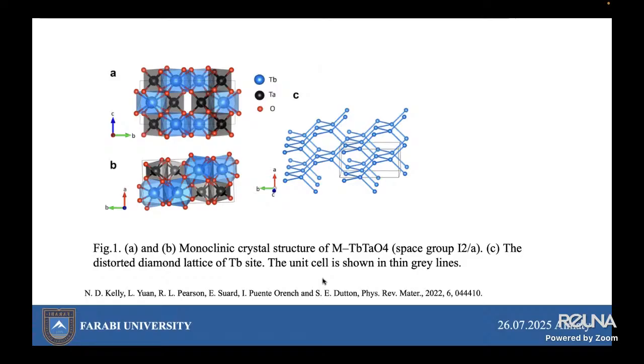Here, below a temperature of 1.2 Kelvin, a slight increase in the angle distortion and the bond distortion is observed from 0 to 6 Tesla. And we interpret this as an antiferromagnetic ordering, triggering magnetoelastic coupling in terbium tantalate.